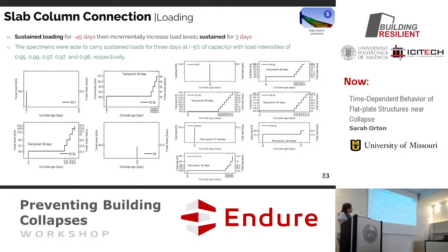Most of them didn't fail under the initial loading. This one did. It took 20 minutes. We loaded it up, and 20 minutes later, it had failed. And this last one, we put it on the loading for about 30 days, then we reloaded it, and it failed very soon after. So it was very hard to get the level of loading, but it was able to hold the sustained load for about 3 days within about 5% of the capacity. I had to get really, really close, inching up on that capacity in order to get that failure to happen. We looked at the bond and the concrete, and they were saying 70%, 80% of the capacity. With the reinforcement acting in there, you can get really close to the actual capacity. And so it's reassuring for our structures that they have that ability.